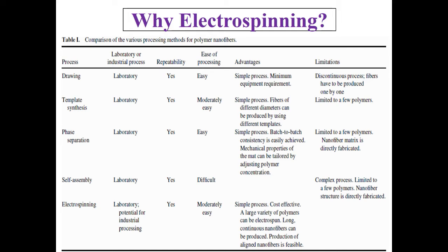Why electrospinning? This table comprises the comparative study between the processes used presently, that is drawing, template synthesis, phase separation, and self-assembly. Electrospinning is very much effective as compared to the other techniques, because whatever the fiber is drawn, that fiber comes into nano size with a very high tension, using a very high voltage parameter. By controlling the viscosity, the pressure, and the drawing rate of the fiber, that fiber can be well controlled with the help of controlling the parameters of that particular setup, and therefore there are very few limitations to this particular method.